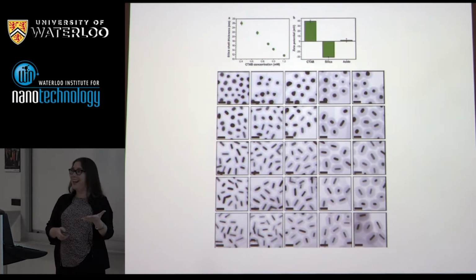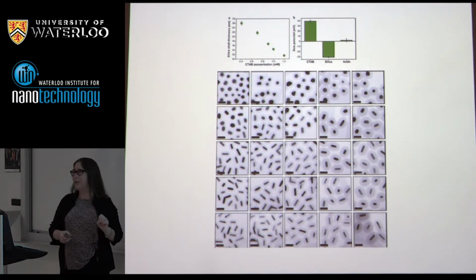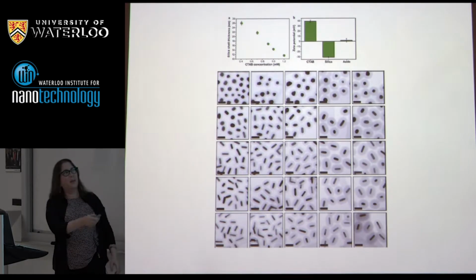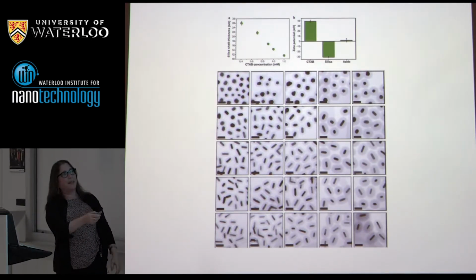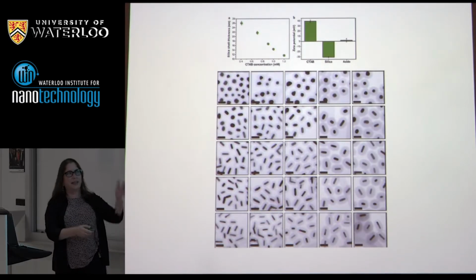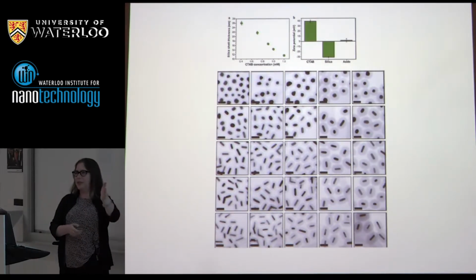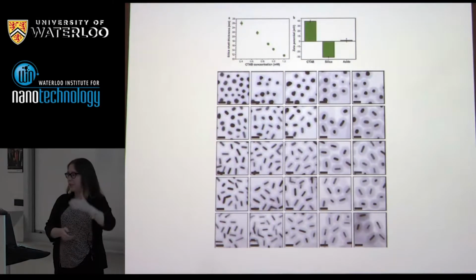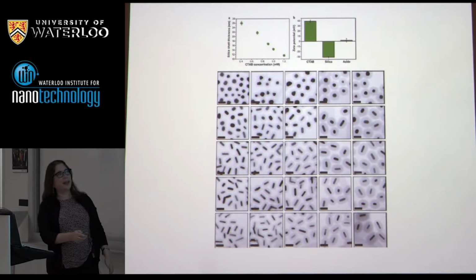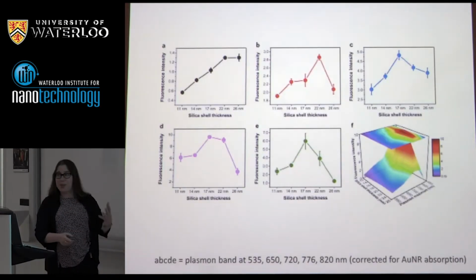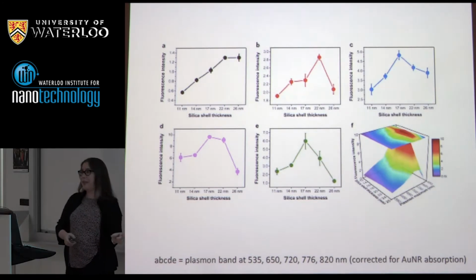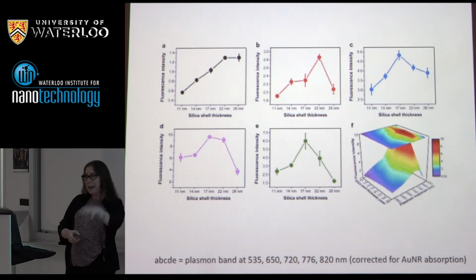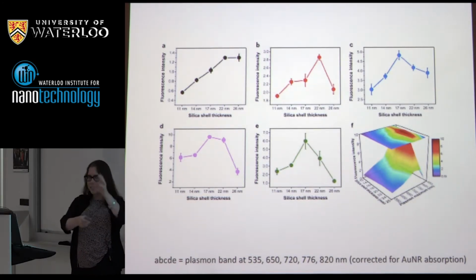How do you know that? Bromide ion selective electrode is the answer. And once you know where you are there, now you're very reproducible and making really gorgeous silica shells here that are 11, 14, 17, 22, 26 nanometers thick, over a certain range. Okay, so that all worked great. And then we go ahead and put on this dye. So we got 5 different kinds of aspect ratios, 5 different thicknesses. So it's 25 experiments here.